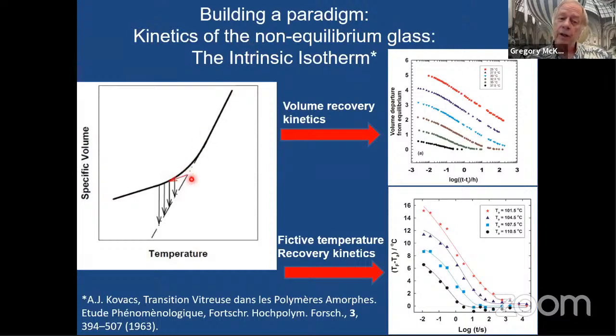So what you do is you start in equilibrium. So what you've done is you've come down to, call it Tg, he called it T0. You let the material equilibrate. Now this is going to be in 100 seconds at this temperature. So it doesn't take very long. And then you're going to jump down in temperature. And what you want to do is you want to watch this volume recover towards equilibrium. And you can watch it recover either by looking at the volume departure from equilibrium, which he called delta, as a function of time.